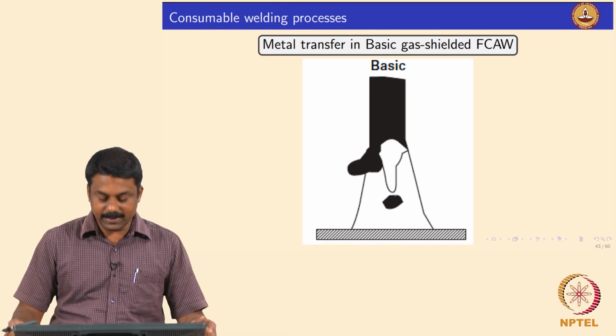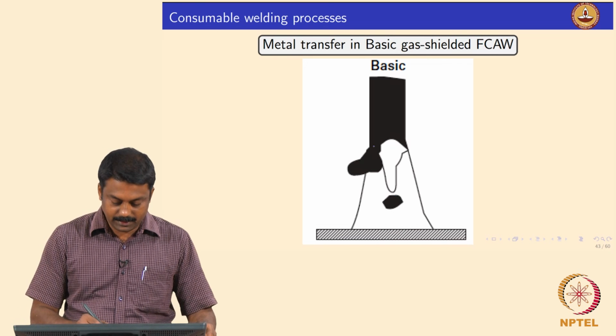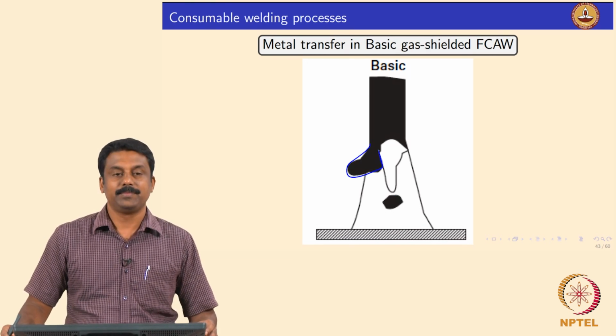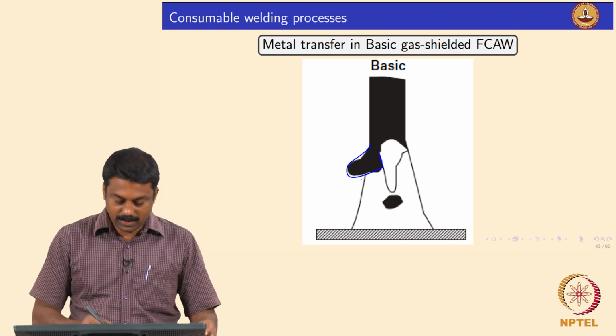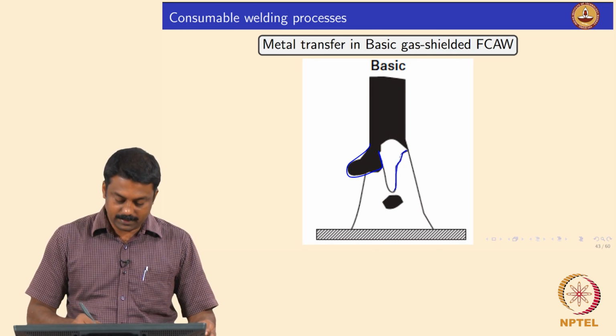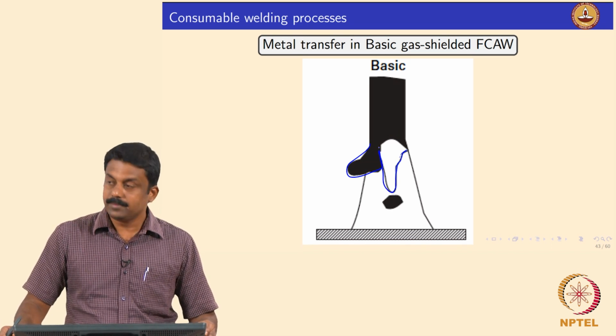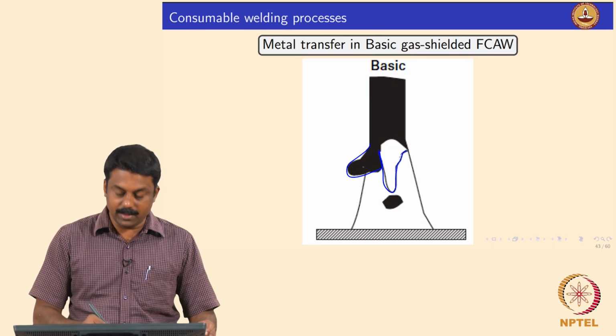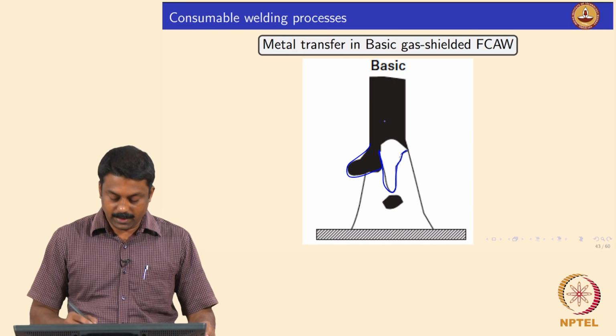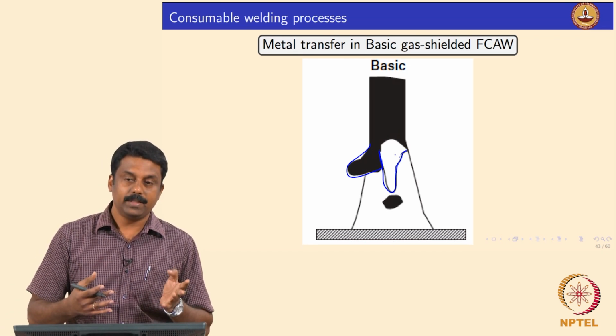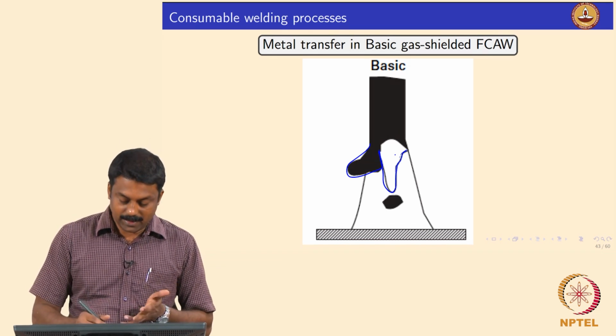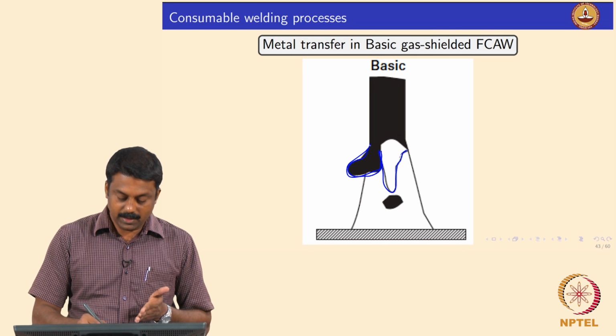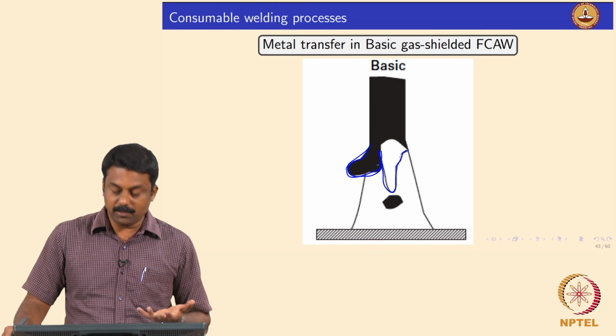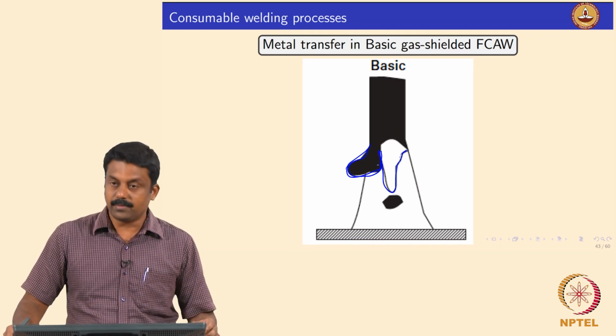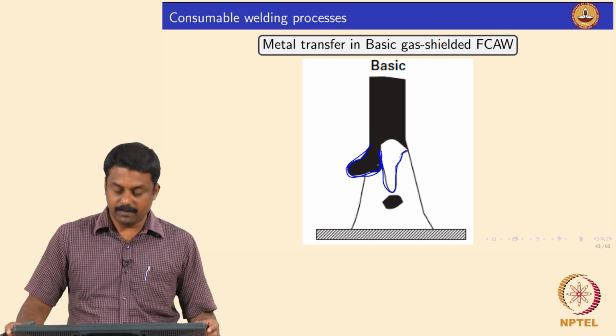So, in the basic steel electrode, that is what I showed you. In most of the cases, the droplet would be attached. And then you would start striking an arc with the droplet, and then you still have a finger developed by the molten fluxes attached to the electrode, which is commonly seen. So, you will have a repelled transfer, and then a finger pattern develops at the electrode tip by the molten fluxes, and by the decrease in surface tension, the molten droplet would be sticking to the electrode tip and forming a repelled globular transfer. Yes, in a basic gas shielded flux cored arc welding.